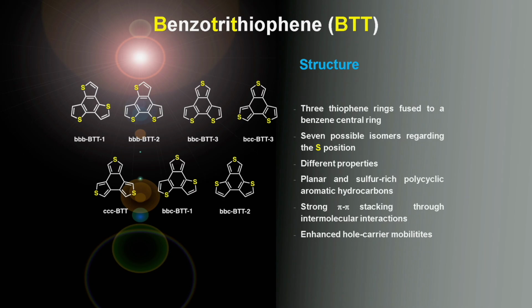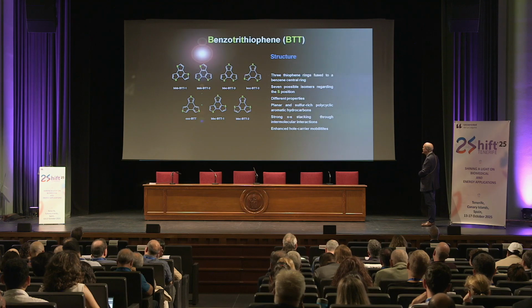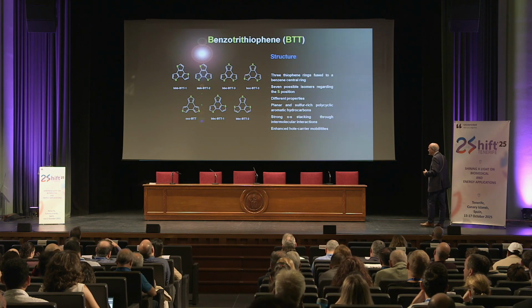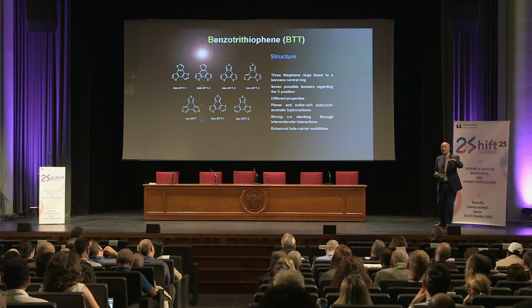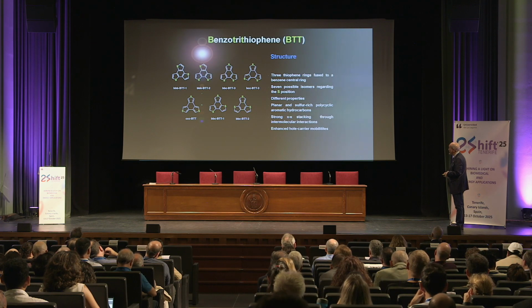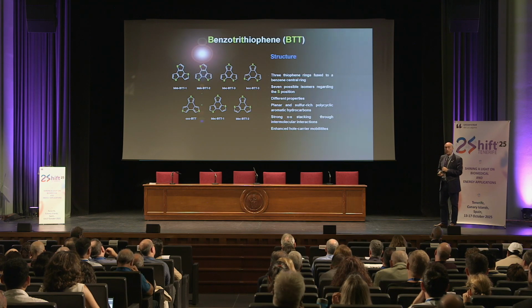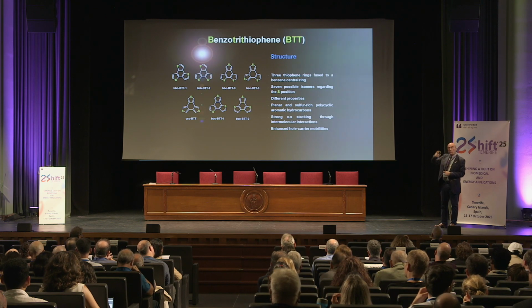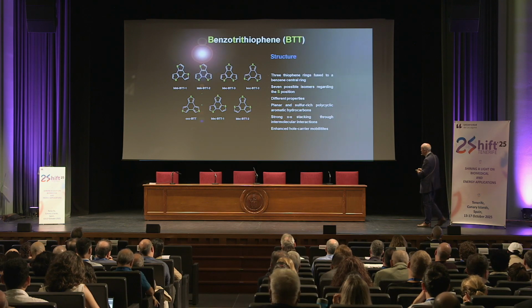So let me show you a couple of examples from our group. We decided to go to benzotrithiophene. If you go to this molecule, this is the central core. There is one benzene ring with 3 thiophenes fused to the central benzene ring. But the question is that there are 7 possibilities for arranging the 3 sulfur atoms. So these are isomers, and they have different properties, but all of them have in common that this is a planar scaffold. And therefore, pi-pi interactions should occur, and this would be good for hole transporting along the material.